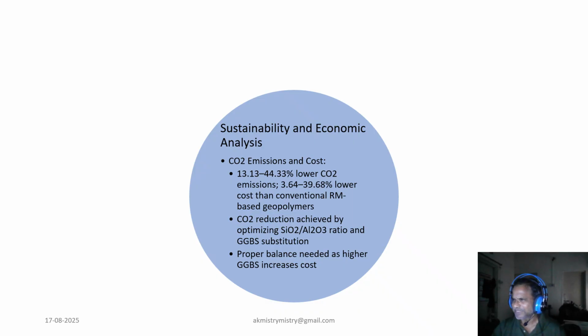Environmental and economic assessment indicated that the optimized geopolymer reduced CO2 emission by 13 to 44% and lowered cost by nearly 40% compared to similar RM-based geopolymers. The silica-alumina ratio played a critical role in controlling emission, with a moderate increase in silica content promoting strength and reducing carbon footprint. However, higher GGBS content, while enhancing properties, can increase cost. Thus, balance is essential.